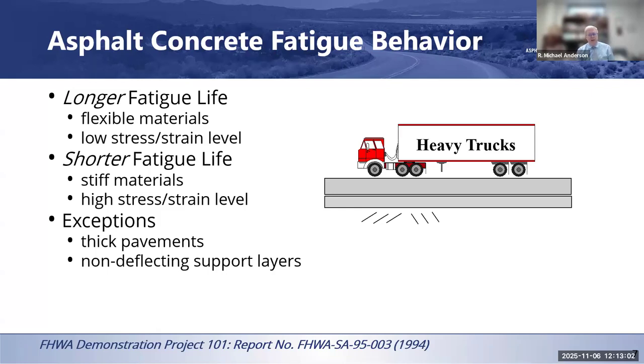So really, to achieve that longer fatigue life, and this is bottom-up fatigue, we're typically looking at more flexible materials that are softer, they're less brittle. The asphalt binder plays a big role in that. And that's important, particularly if the asphalt structure, the pavement structure, is relatively thin. Reducing the strain in the asphalt mixture is really going to help out. So if you make the pavement thicker, you're reducing the strain before you get to the bottom layer. That's really going to help reduce that strain overall, and it's going to help you with your performance.